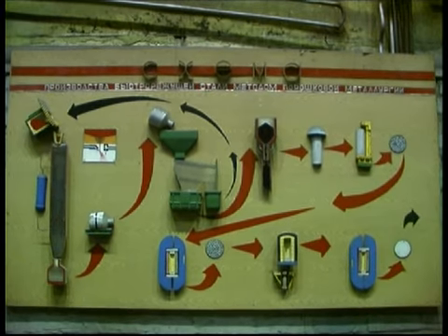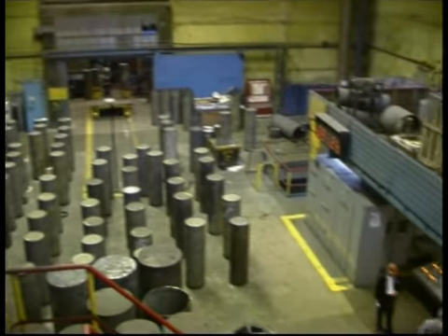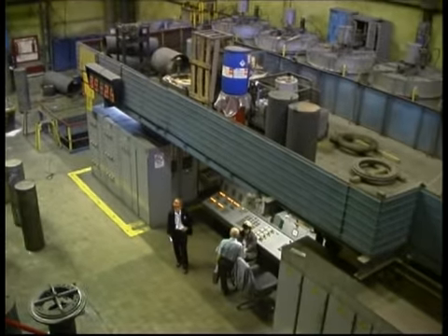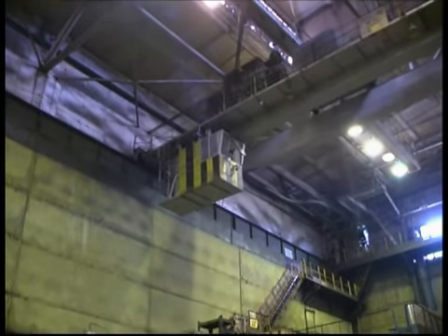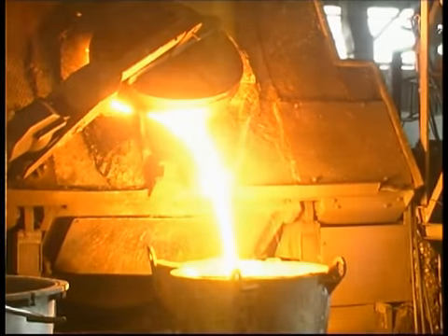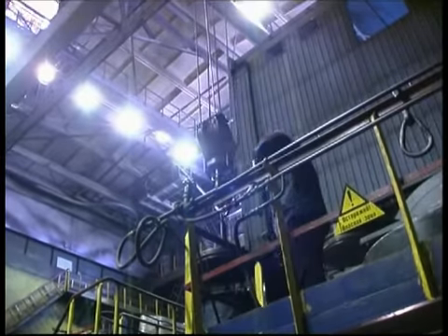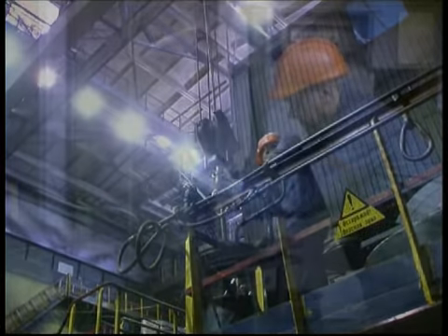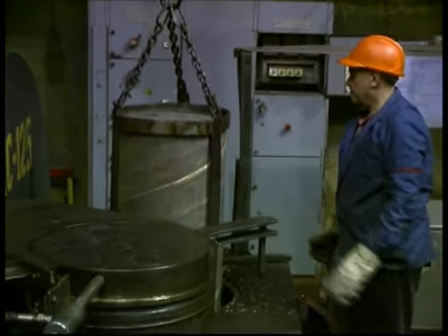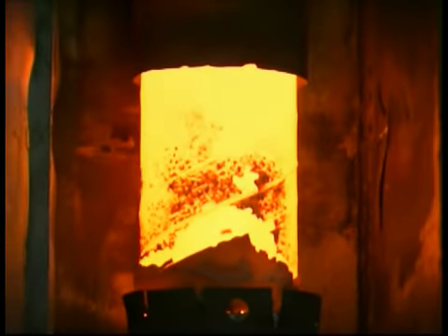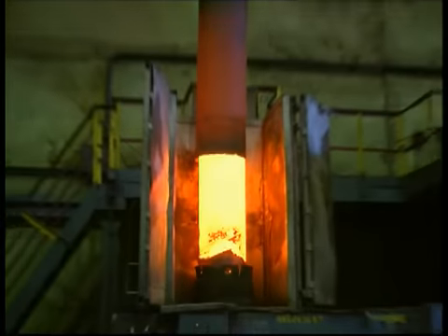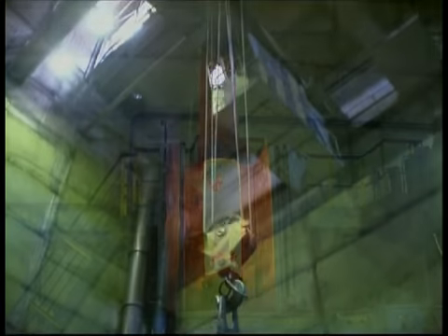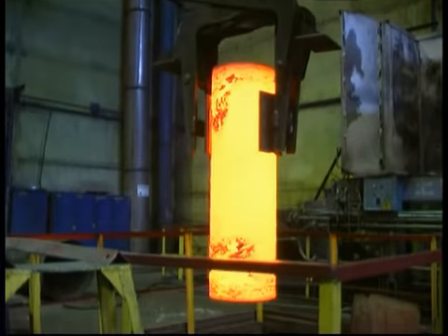Since 1980, the powder metallurgy shop has been producing high-speed and ledeburite tool steels. Swedish technology ASEA Stora applied at Dneprospettstal includes steel melting in an induction furnace, atomising into powder, welding into sealed capsules with further cold isostatic and hot isostatic pressing at the temperatures 1100 and 1150 degrees Celsius at the pressure 1000 atmospheres. The obtained structure is characterized by homogeneity and shows no evidence of carbide banding. In this case, grain size is significantly finer than after an open melting process.